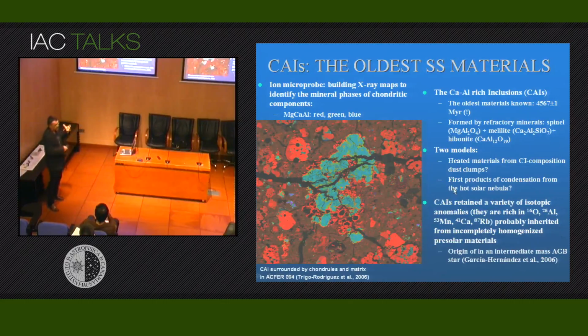So the CAIs retain in these minerals a big variety of isotopic anomalies. They are rich in oxygen-16, aluminum-26, manganese-53, and so on, that are probably inherited from the incompletely homogenized presolar materials in the solar nebula. It's a mixture between the gases that were coming from nearby stars and the solar nebula materials. That is a very, very exciting conclusion of this study.